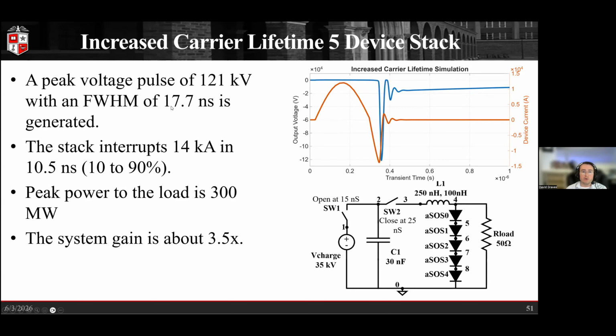And we can see the full width half max of this system is 17.7 nanoseconds. And we're breaking 14 kiloamps in 10.5 nanoseconds. Again, that's the 10 to 90 time. And we're getting that peak voltage of 121 kV with only initial charge of 35 kV. So we get a system gain of about 3.5x, and we actually deliver 300 megawatts to the load.